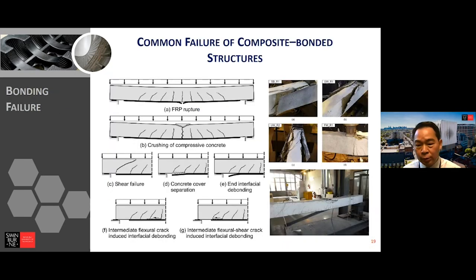So we can take composite repair of concrete structures as an example, to see what is good bonding, what is bad bonding, and poor bonding. When you look at all these diagrams, using composite to repair concrete structures has been done for 20 years. I remember the first few years there were a lot of problems because the bonding was no good and could not get a very strong bond between the composite material and the concrete. So when you look at all this,